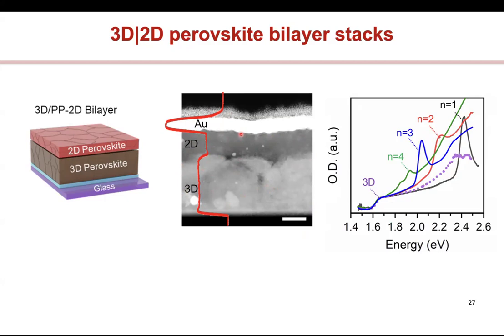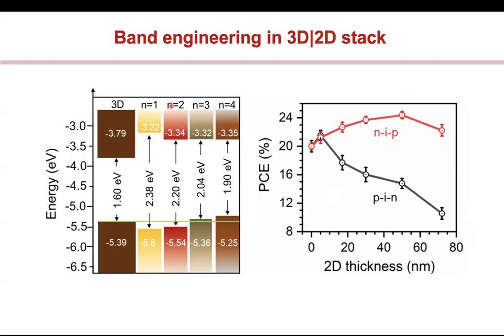Okay. And now what I can do is I know these band gaps of the 2D and I know their energy levels. I can now use them as selective contacts. For example, it turns out that for a 3D perovskite here with a band gap of 1.6, you can see that if I want to inject an electron into a 2D, it's too high, which means there's a barrier for the electrons, but there is no barrier for a hole if I pick this layer here, right? The holes can go through seamlessly. And in fact, that's what we find, that I can make these devices which are called NIP. Essentially, you have holes which will go from the perovskite to this n=3 layer of the 2D and then go out, and I can control this charge transport through this behavior.